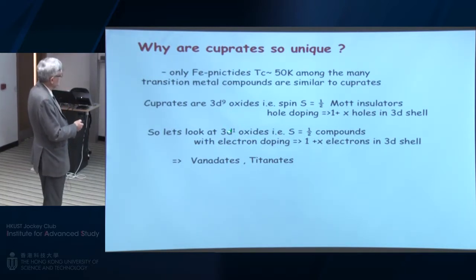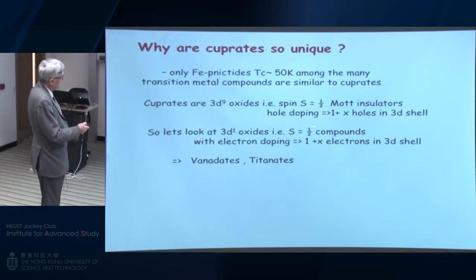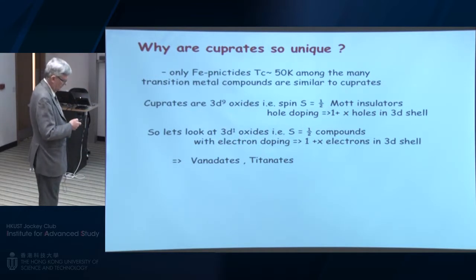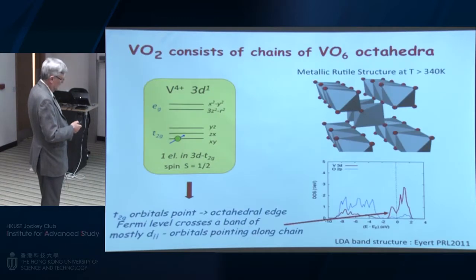So you might think, well, if we put in 1 hole and we get superconductivity, let's look at what happens if we put in 1 electron in the 3d shell. That again will be S equals 1/2, and instead of having 1 plus x holes, we have 1 plus x electrons. Well, that brings us to a set of compounds known as the vanadates. Let's take a look at these vanadates and see what happens. So we now have this 1 electron down here, rather than 1 hole up here. Now this is in a set of orbitals which don't hybridize as strongly as with the oxides, because now the maximum in xy is pointing towards the center of an edge of the octahedron. So these are the d orbitals that point towards this edge here.